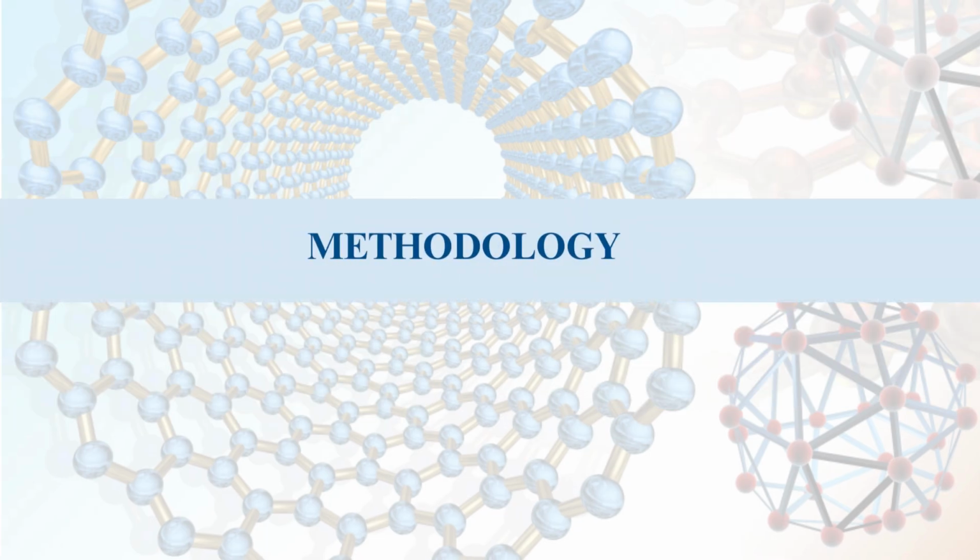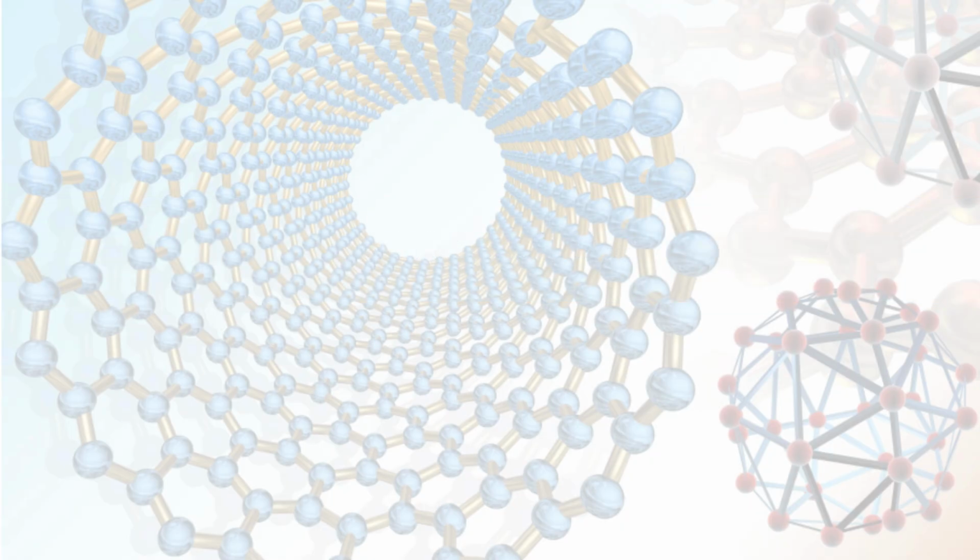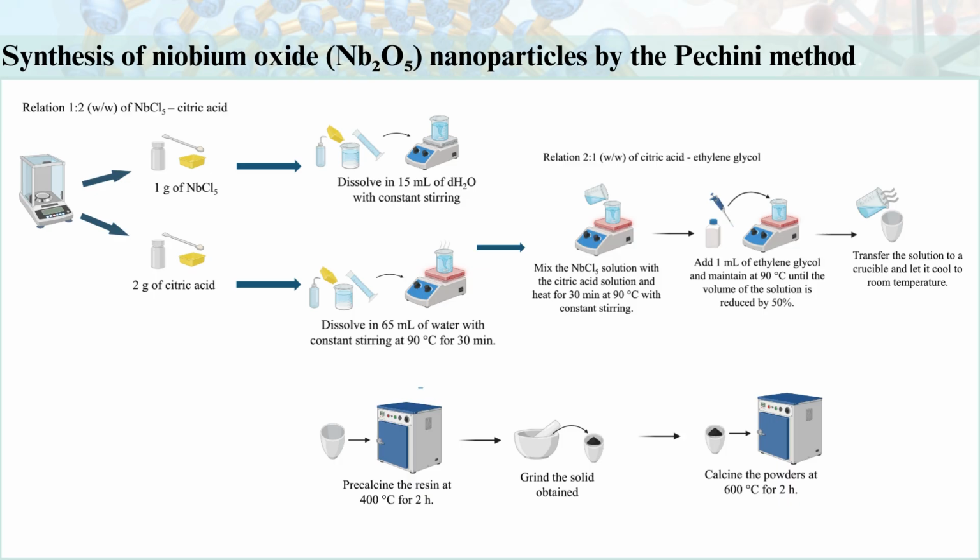To confirm our hypothesis and meet our objectives, the following methodologies were carried out, which are based on the synthesis and characterization of nanomaterials and their in vitro evaluation. The synthesis of niobium oxide nanoparticles was carried out using the Pechini method, which is based on the formation of a metal complex using a chelating agent, citric acid, and a polymerizing agent, ethylene glycol, which is then subjected to a thermal process to obtain the desired metal oxide.